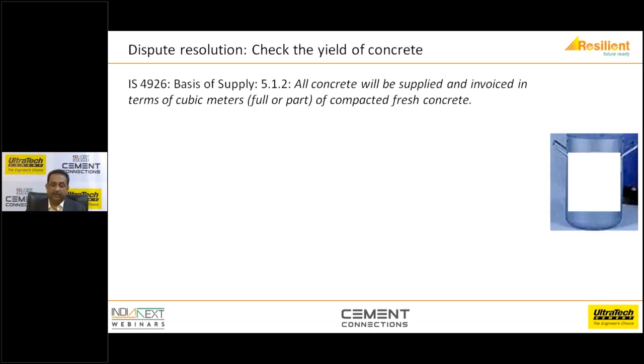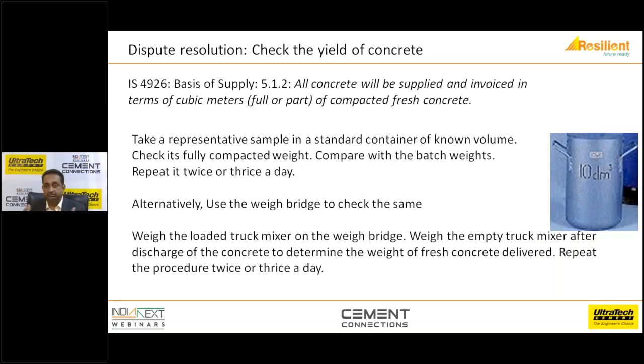And when you check for yield, one way to do it is to take a standard container of a known volume, maybe a 10 liter sample container, take a sample of concrete, fully compact it, and find the weight. The weight divided by the known volume will give you the yield of the concrete. So in this way, you can find out whether there is a difference from what the design mix is telling you, and whether there is a problem with the batch weights or not.